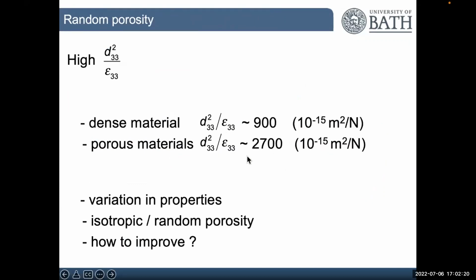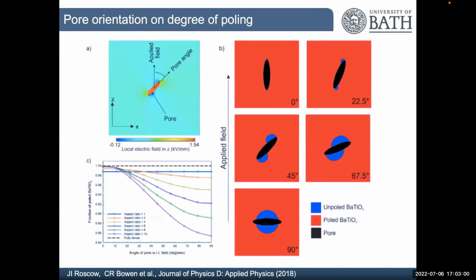And certainly by making the material porous, we can get pretty large improvements in some of these figures of merit. So making a highly porous material, we can go from a dense material, because of its high permittivity, which has a value of 900. Don't worry too much about the units. It's just a figure of merit, a relative assessment of performance. But by making it porous, by maintaining the polarization but reducing the permittivity by adding porosity, we can get up to 2,500, sometimes 4,000.